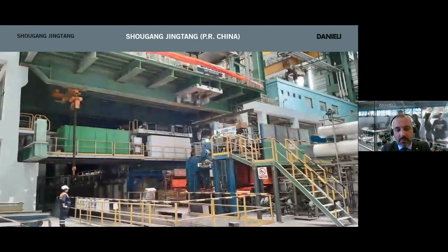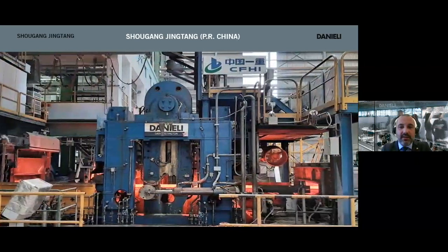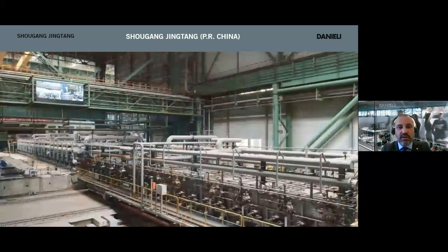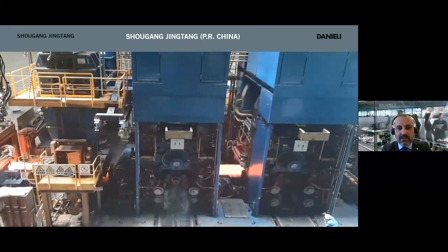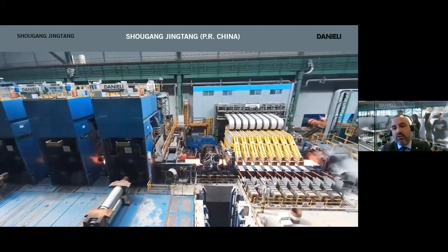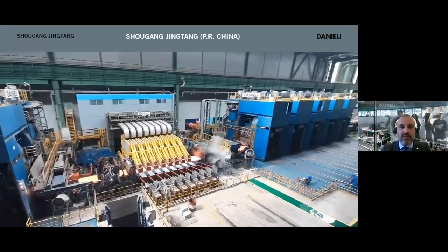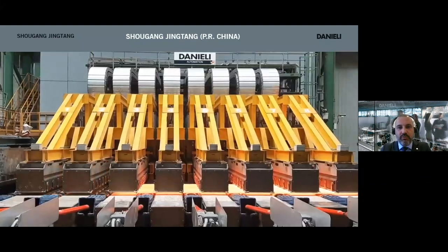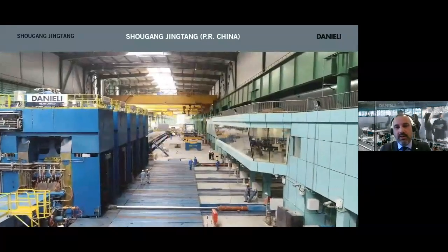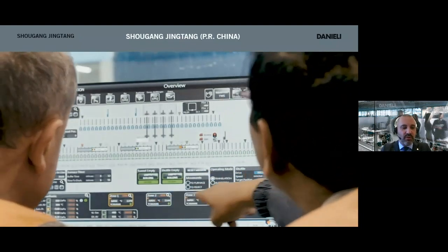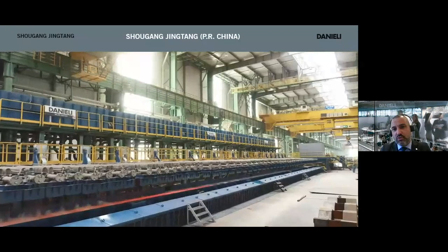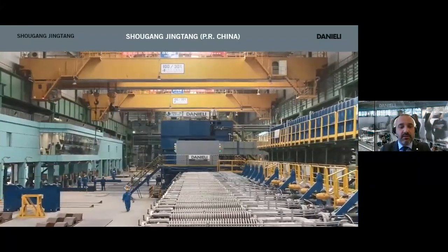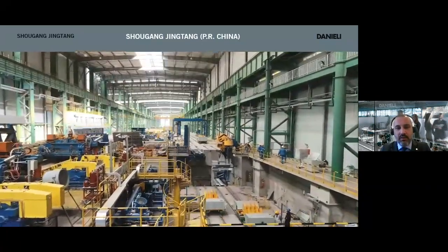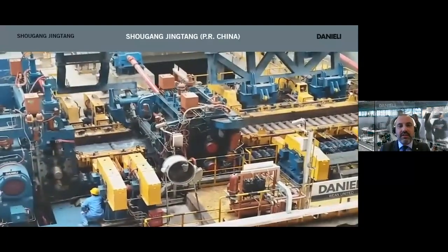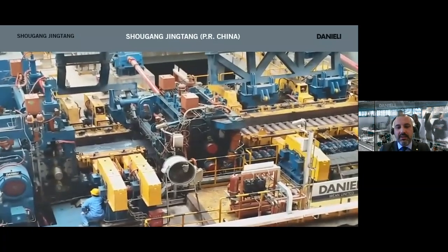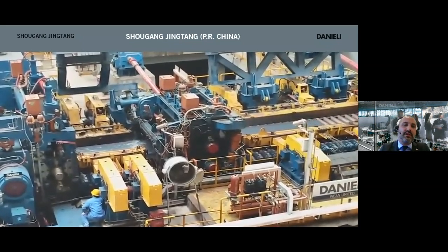By exploiting the flexibility of the Danieli Universal Endless plant, as we mentioned earlier, there is of course regular application of the work roll change during production without affecting the casting operation, thanks to the tunnel furnace that, although shorter than conventional USP plants, has enough buffer time in order to perform a 10 minutes work roll change at the finishing mill without stopping the caster, so keeping as long as possible the sequence length. At the same time, also during casting the mold width adjustment is applied regularly, up to 100 millimeters so far, which is recovered by the edger installed at the entry side of the reduction stand, and therefore exploiting at the maximum possible level the yield of the plant.